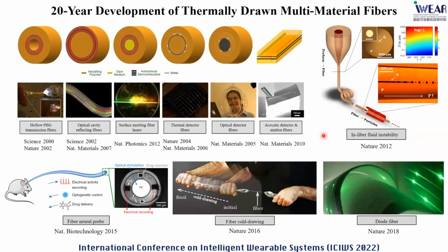has been developed over 20 years, since the first demonstration in the early 2000s. We have achieved a lot of functionalities. For example, in the early stage, light transmission, then gradually moving to surface-emitting lasers, and thermal detection, optical detection, and acoustic detection. The functionality of this fiber is not limited to the fiber itself. We also studied, for example, different physical phenomena inside the fiber, such as fluidic instability and geometric instability.